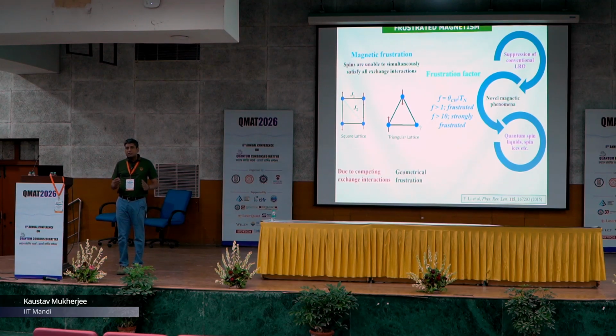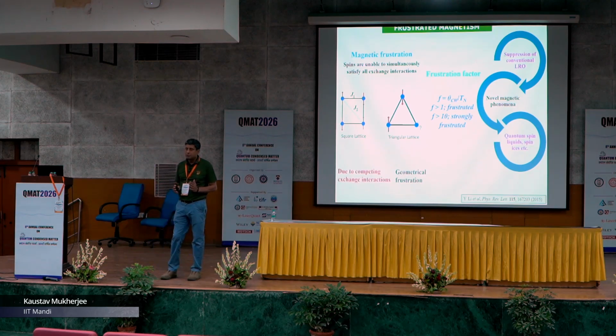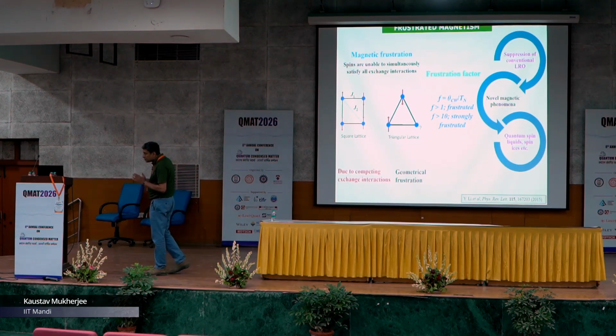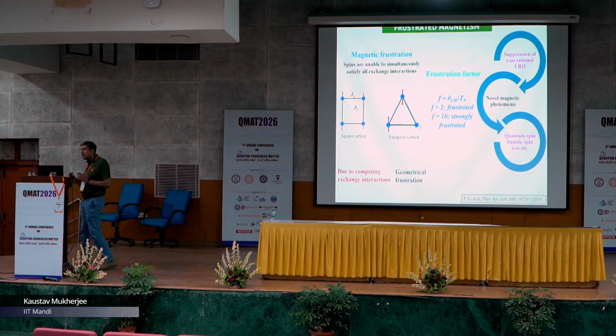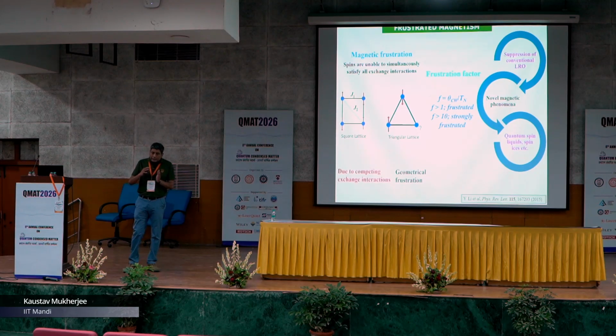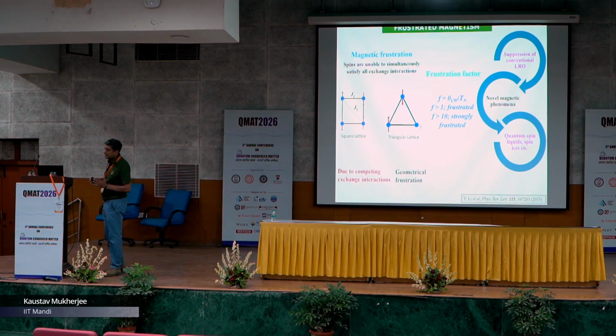Now, why are we all discussing this frustration over the last 3 days? So, what happens if a magnetic system is frustrated? The first condition is that in a frustrated magnetic system, long range ordering is suppressed, but it does not imply that the system becomes a non-magnetic system. Due to suppression of this long range ordering, many novel magnetic phases evolve, like a spin liquid phase or a spin ice phase or effective spin half state, etc. All these novel phases are worth investigating. Hence, these frustrated magnetic systems become important.